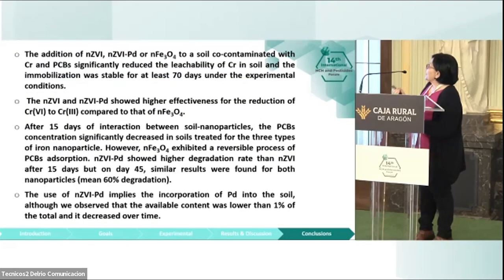In general terms, as conclusions, this is a summary of what I explained. The addition of the three types of nanoparticles does lead to a reduction of leachability in soil, and it leads to immobilization for at least 70 days. So this would be ideal for chromium. Both the nano zero-valent iron and the one with palladium showed higher effectiveness for the reduction compared to nanomagnetite.